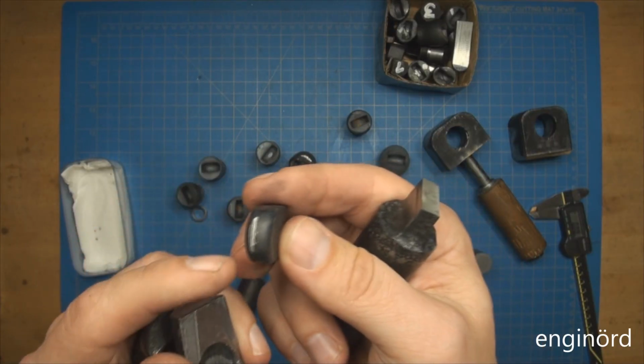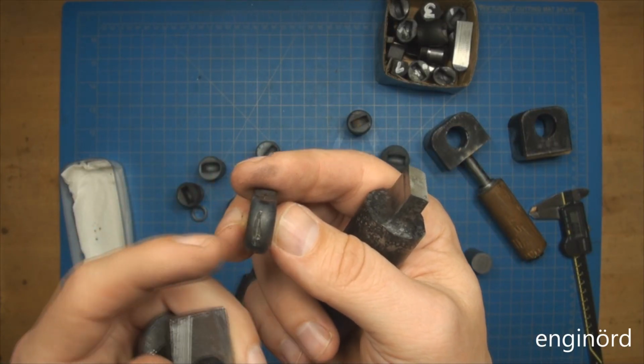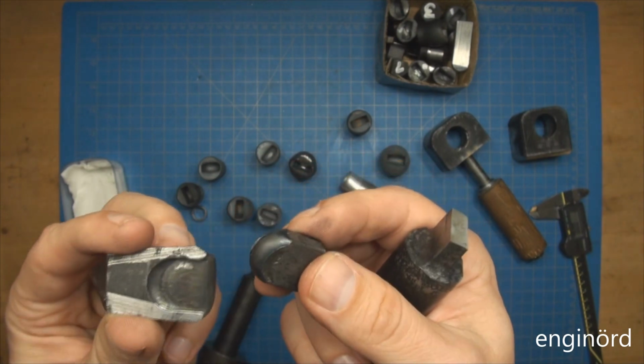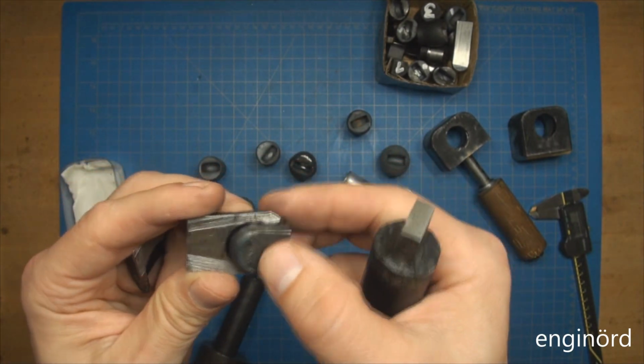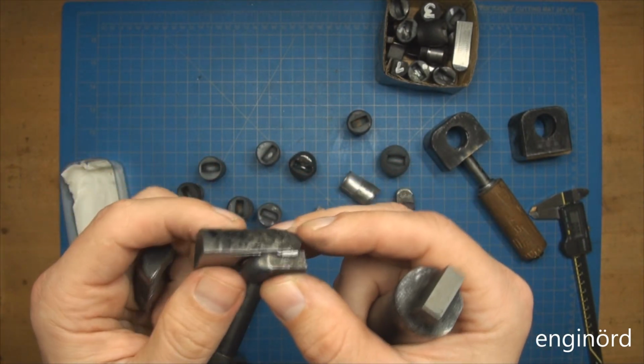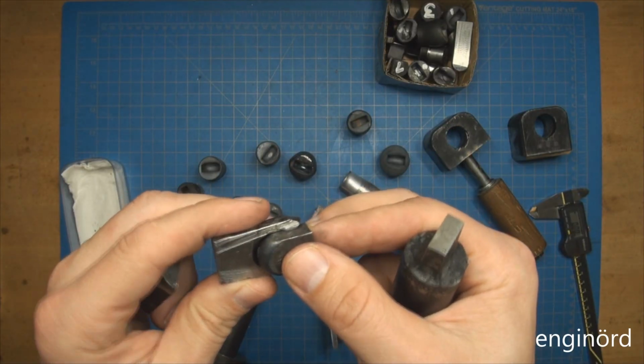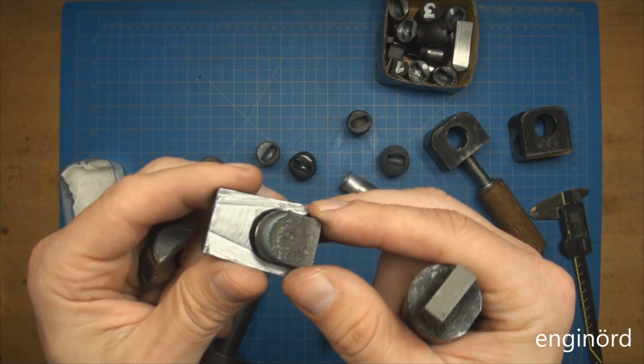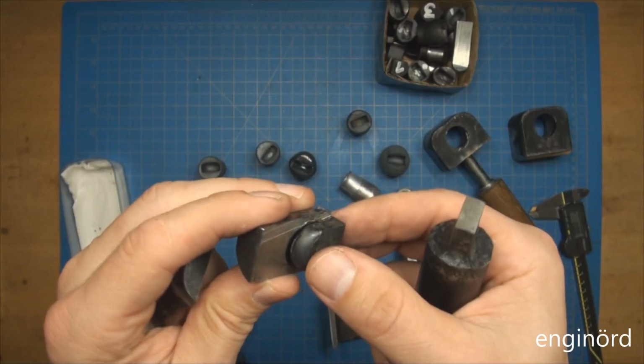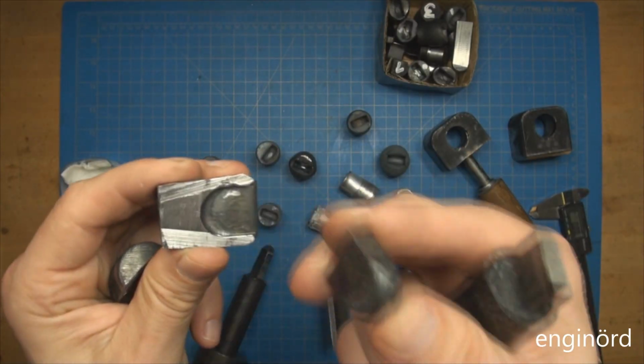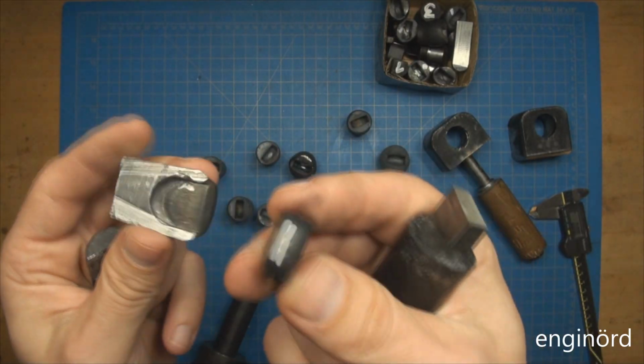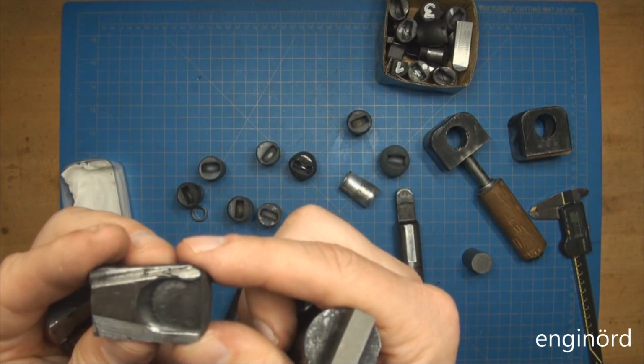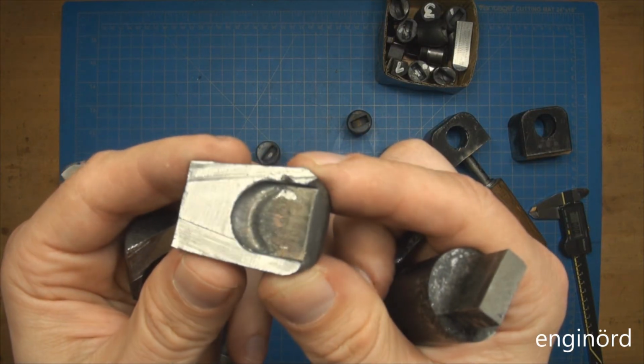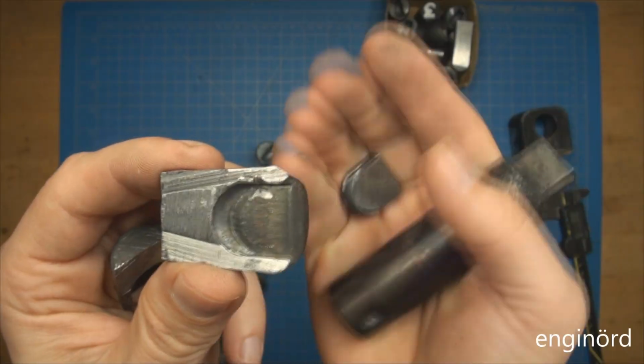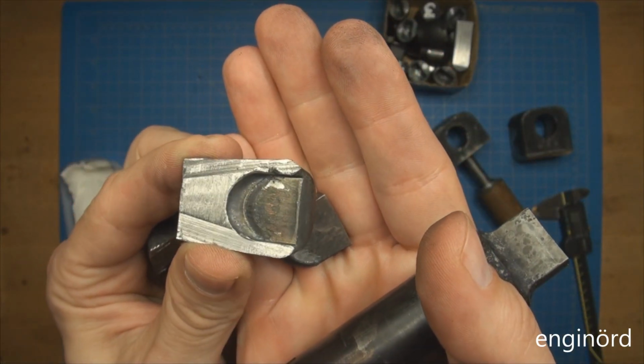And you can see that the saw cut into this, but it doesn't matter because this was already annealed. So when this broke into that, this was like red hot, white hot, and it just cooled down slowly, and it essentially annealed this tongue or tip of the tool. And by the way, you can also see how the cavity looks after the forging process.